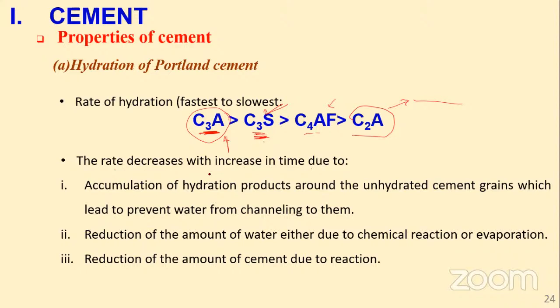Why? Because these materials are reacting in the same environment. Okay, if it's in a container where you are mixing, they are reacting. So the hydrates that form, calcium silicate hydrate, when they form and precipitate, they cover the other unreacted particles, which means that now water to percolate, to penetrate, to reach these unreacted particles takes time. And that's why the rate of hydration will decrease as the accumulation of hydration product around the unhydrated cement grains, which will prevent the water from channeling into them.